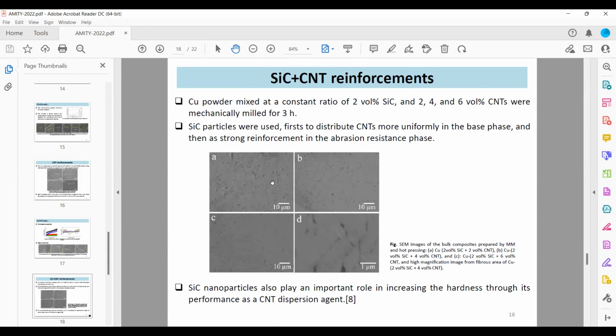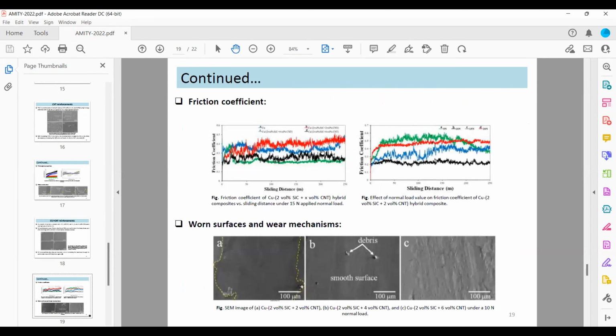These images show pore-free structures, and a strong interface contact was established. As silicon carbide is one of the hardest ceramic particles, the nanocomposite hardness also increases. The wear and friction coefficient also show that the reinforcing phase acts as load bearing elements, so they reduce the contact area with the sample surface, and the wear is reduced.